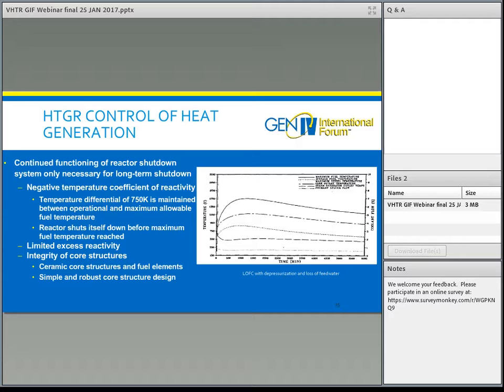Furthermore, there's a lot of redundancy in the control of heat generation in the reactor. We talk in reactor safety terms about a reactor shutdown system. What would be needed to ensure the reactor shuts down and stays down? And so, as noted here, a reactor shutdown system is only necessary to guarantee a long-term shutdown condition for these reactors. The temperature differential between the operating temperatures and the maximum allowable fuel temperature is so great that there is not a chance of fuel damage in this reactor. The reactor shuts itself down before the maximum fuel temperature is reached.